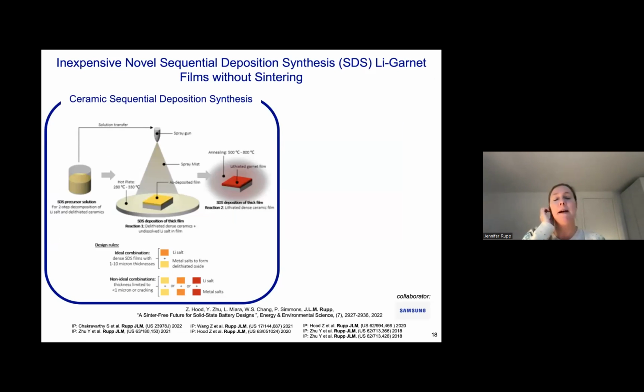So here's what we came up with in collaboration with Samsung. We invented a method called ceramic sequential deposition synthesis. The idea is to have literally a spray gun where we offer all the metal salts of the lithium garnet as cations, as a salt, and we bring them in a high boiling point organic. Then we bring it to a spray gun, let it rain, and create a mist where the droplets hit a heated substrate, undergo pyrolytic decomposition, and form the metal oxides. This is what you can read in a ceramic textbook.